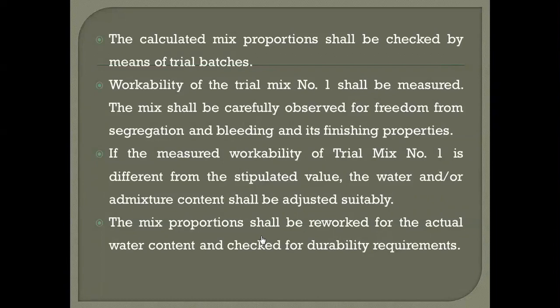After doing the first trial we have to carefully observe the workability, and after 7 days or so we have to check the strength of it. We have to check whether it is nearing 30 or not. Then if there is segregation or bleeding, that also we have to check. Then only we go for the second trial. If everything has failed in the first trial, then we go for a second trial. There we have to do some adjustments till we get the required strength, workability, and other parameters. So this is how we have to do the mix design.